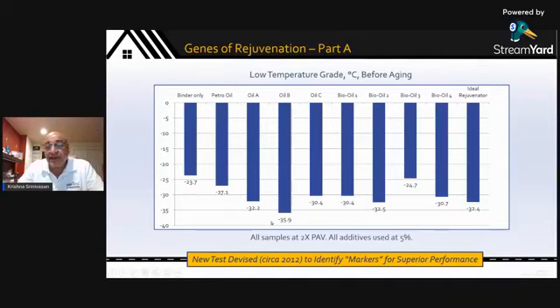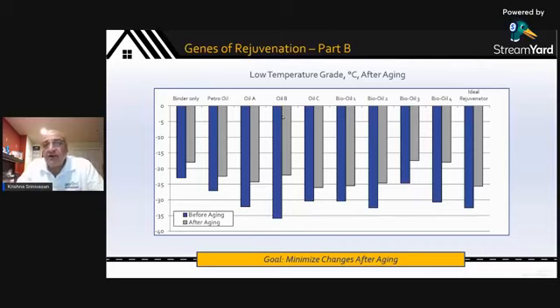So we added about 5% of this to this aged binder, and we looked at the low temperature properties. And right away, if low temperature property, as I mentioned to you, is a good proxy for performance out in the field, you can see oil B gives the most dosage efficiency. For 5%, it's able to give you the best low temperature performance, until we did one more step. Remember, I told you we created artificial binder that was similar to, let's say, 3 to 5 year, 7-year roadway extracted materials. We took all of these materials and subjected them to one more aging cycle to try and see, okay, you make a roadway with petro oil A or bio oil 2 or oil B or oil C. What does the long-term performance look like?